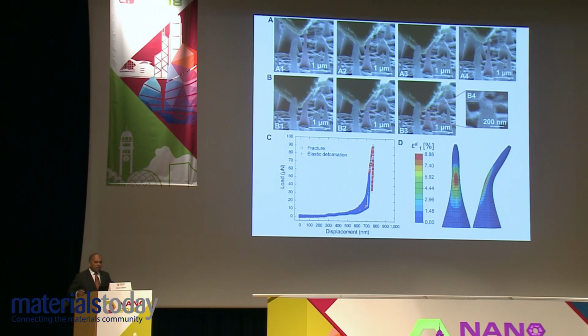Figure C shows the load displacement curve for this failure mode of pushing diamond. You see an elastic response. The blue data points show the deformation before catastrophic fracture. So we unload it, we go back, and then we reload it. You see a little bit of hysteresis because of friction between the diamond tip and the nano needle. But if you redo the experiment after unloading, if you reload the same nano needle, you see the red curve. And in the case of the red curve, we go all the way to the point of fracture where the diamond catastrophically fractures. To your extreme right is the finite element simulation that takes into account anisotropy and nonlinear elasticity.